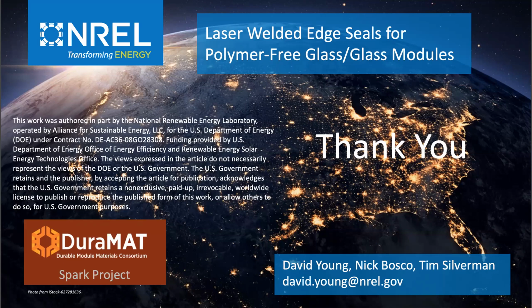joints. But the other thing I wanted to mention was this type of embodiment would essentially eliminate the driving force for cracking cells, since the cells are unconstrained within this glass structure. There's nothing to transmit stress from a deflected module to the cells. So it would be almost impossible to crack cells in this module. Awesome, thanks.